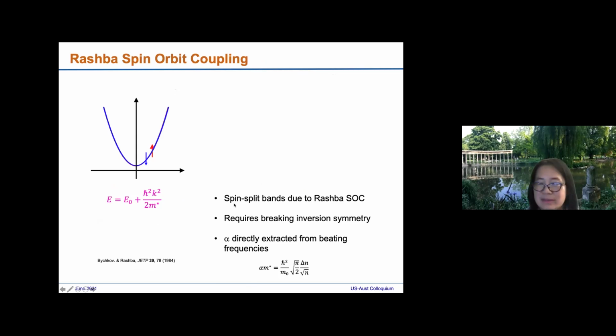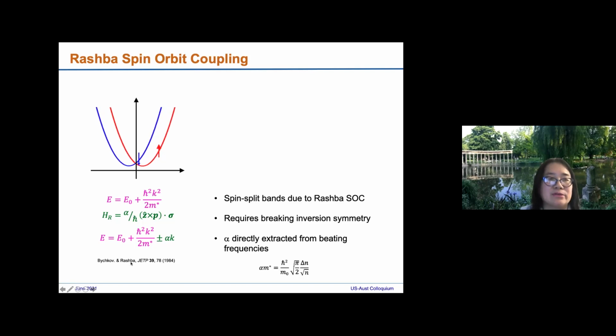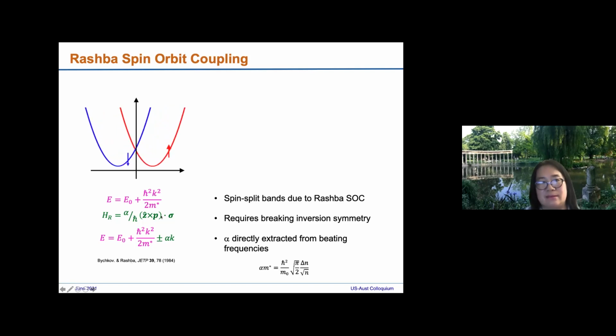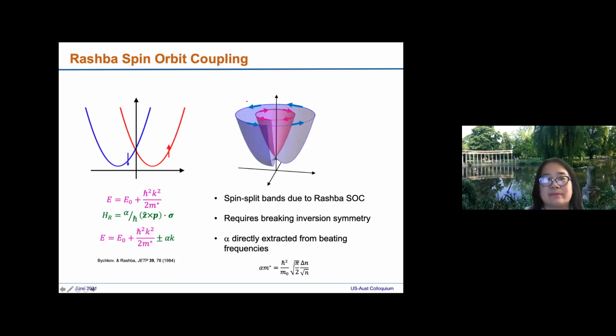So what is Rashba spin-orbit coupling? If you have a normal semiconductor, the band looks like that. If you add the Rashba term, the energy becomes plus or minus alpha, which is the Rashba parameter, times the momentum k. So it splits horizontally, and this gives us bands like this.